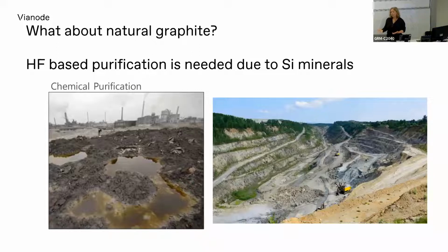Most of the chemical purification that is done requires a large amount of hydrofluoric acid. Because graphite is a naturally occurring mineral, it tends to have a lot of silica deposits in it, and silica is very difficult to get rid of. Really, the best way to get rid of it is to dissolve it with hydrofluoric acid. If you have worked in industry, you might know hydrofluoric acid. It's quite nasty. It is a weak acid, which sounds like it would be nice, but because it's a weak acid, it can go through your skin and into your bloodstream and cause the calcium in your bloodstream to precipitate, which can give you a heart attack. It's also extremely corrosive and bad for the environment.